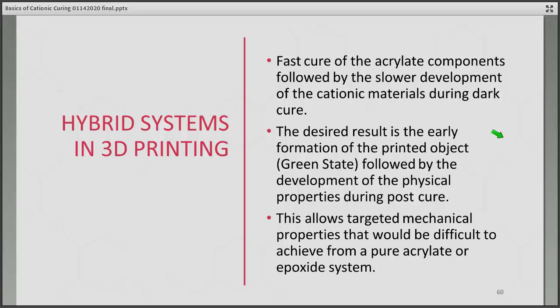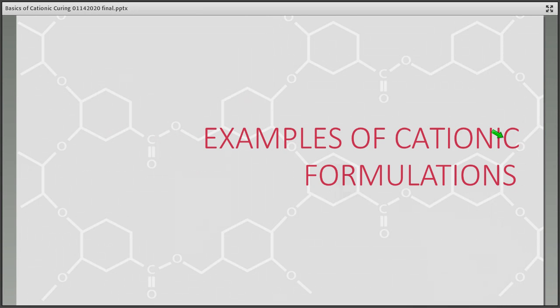The desired result is that you get the formation of your printed object very quickly, known as the green state. The acrylate is formed, you take it out of your bath, and you can handle it without breaking or deforming it. And then you let the final physical properties form during post-cure. So this allows targeted mechanical properties that would be really difficult to achieve from either a pure acrylate or epoxide system.